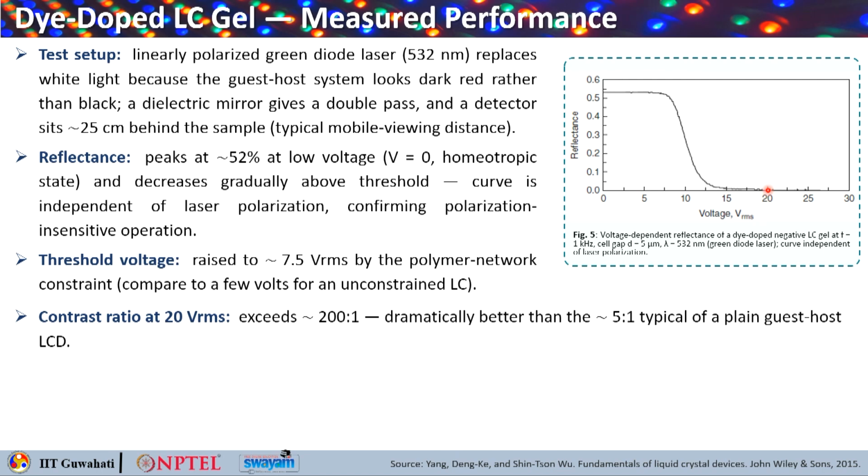If you compare this explicitly against the roughly 5:1 contrast ratio that we were getting earlier from the typical pure guest host kind of display, this is roughly 40 times more than the previous one, by adding this scattering on top of the absorption.